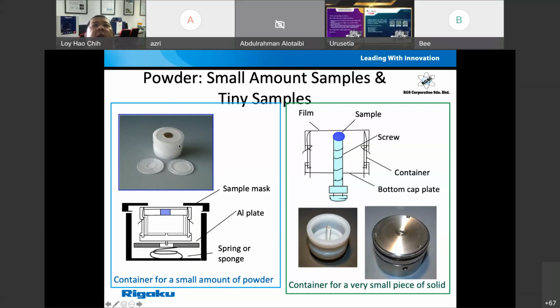Then you put it in the X-ray cups and you put it in the measurements. Okay, this is one thing. If you have a very small piece of sample, maybe 1 mm, 2 mm, or 0.5 mm, either a solid piece or a tiny bit of sample or powders, you can stick them on the top of this screw. This is an acrylic screw that you can stick your samples on top. Then you put it in the cups, then you go for the measurements. This is an additional accessory that you can use with this kind of sample preparation.